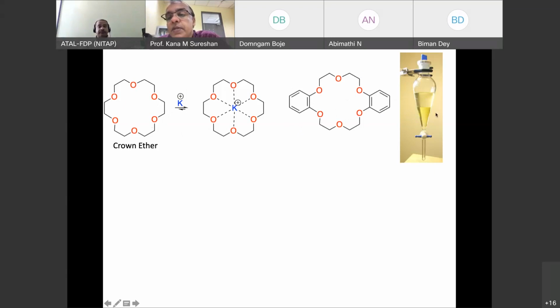and then take out the potassium from the water layer by shaking in a biphasic extraction manner. Because if you take the solid directly, what you see in the absorption is only potassium picrate. Actually, the yellow color is picrate. So if you dip this tablet in potassium picrate, only surface activation happens. So it takes potassium picrate only on the surface. Most of the inside of this crown ether is inaccessible to the potassium ion.